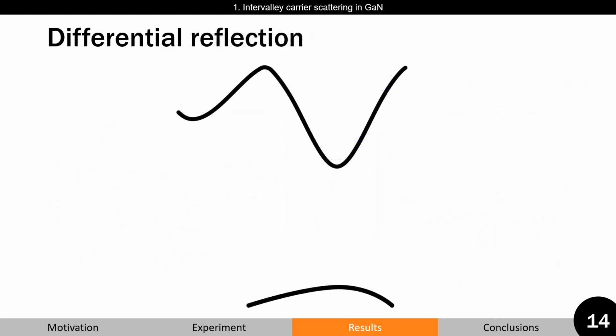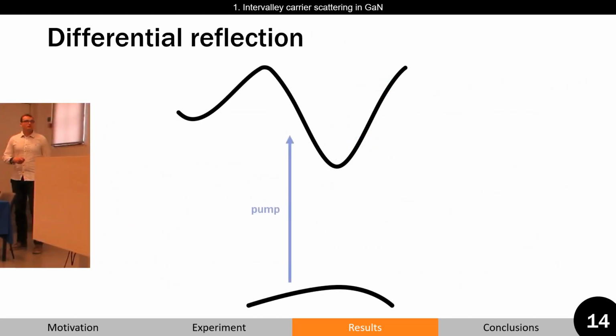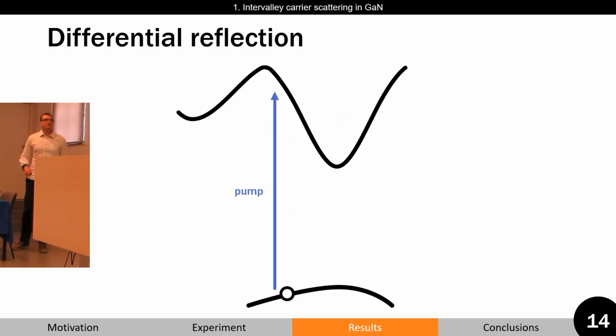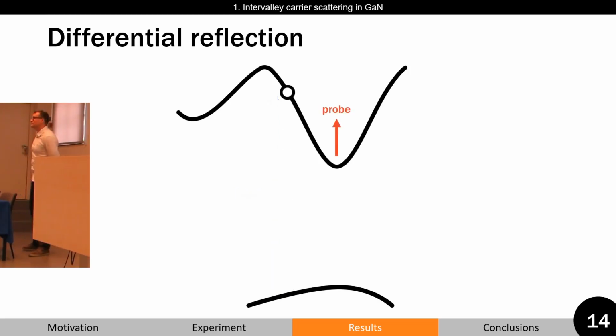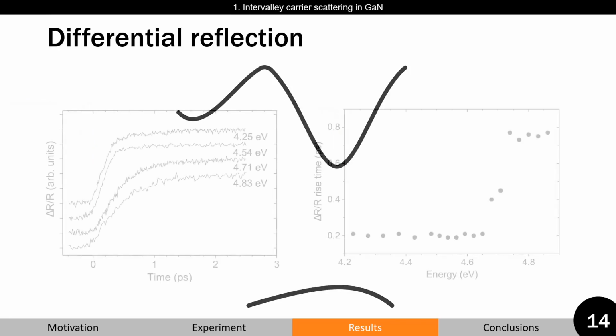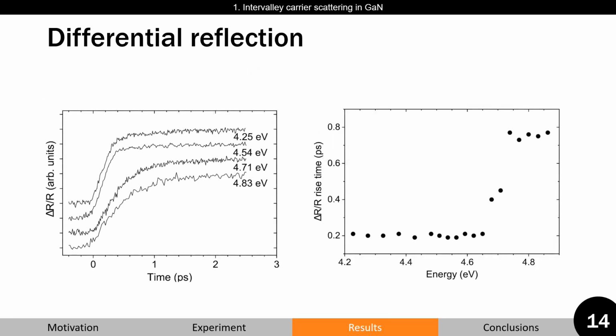In differential reflection measurement, a UV pump was used to excite electrons from the valence band. Here again, if the pump energy is below intervalley energy, one should expect to measure fast processes. In case pump energy is able to induce intervalley carrier scattering, then transients are expected to slow down. This is also confirmed with experiment. With increased pump energy, rise times slow down, and plotting rise times versus pump energy reveals a second threshold-like behavior.